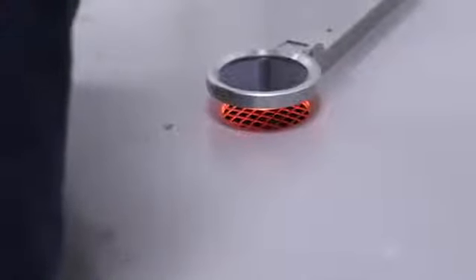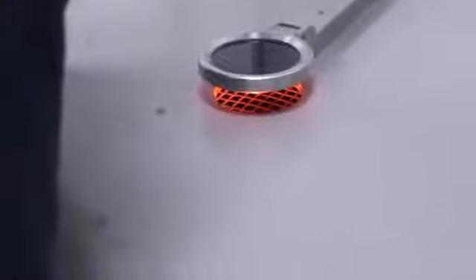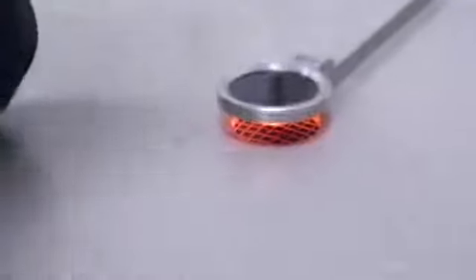Once the metal has reached the casting temperature and the heated casting ring is in position, the machine is released and the spring triggers the rotational movement. As the metal fills the mold, a hydrostatic pressure gradient develops along the length of the casting. The pressure gradient from the tip of the casting to the bottom of the surface is quite sharp and parabolic in form. When the casting process is completed, the mold is removed from the casting machine and allowed to cool down according to the manufacturer's instructions.